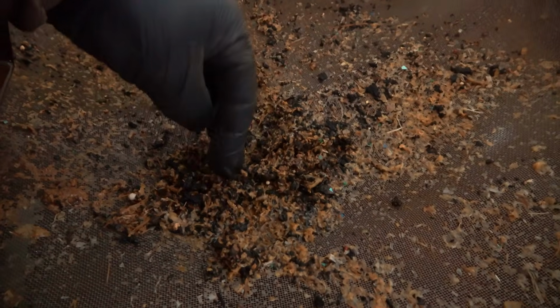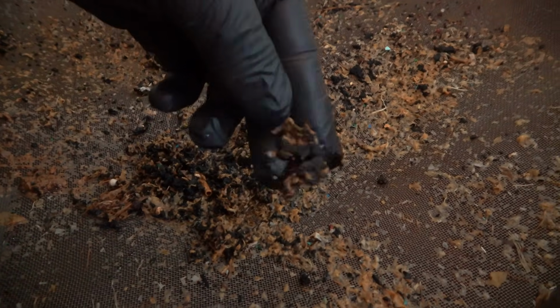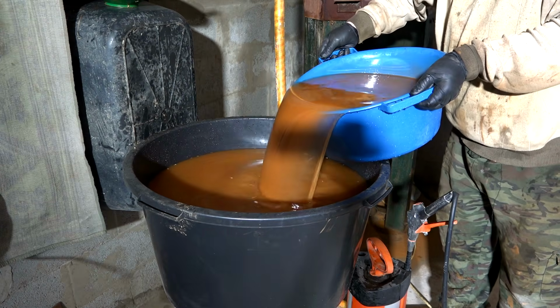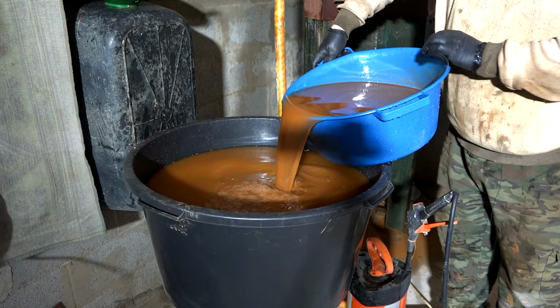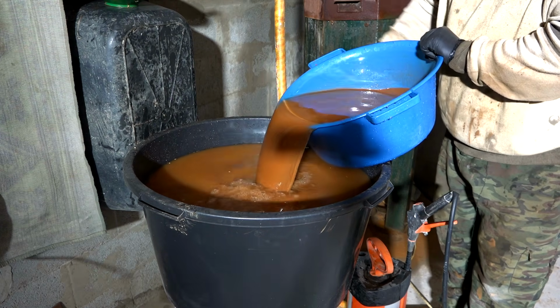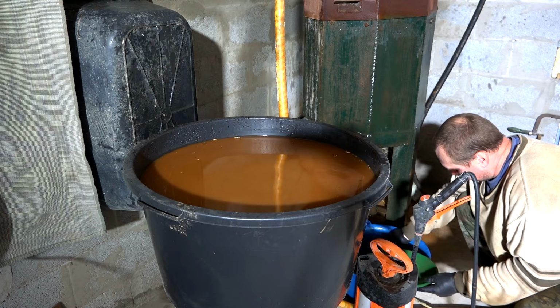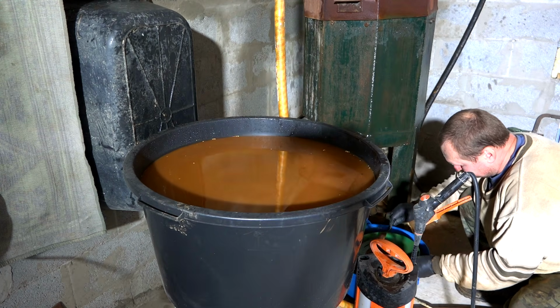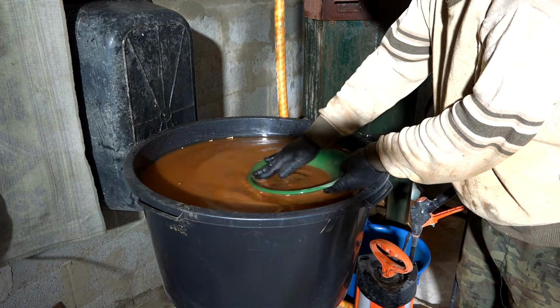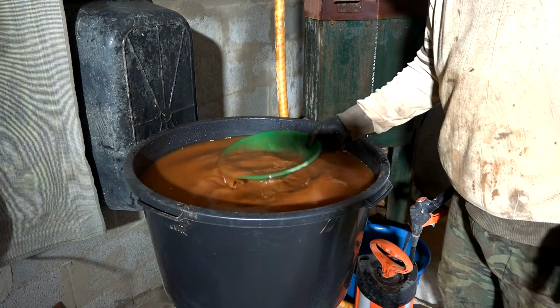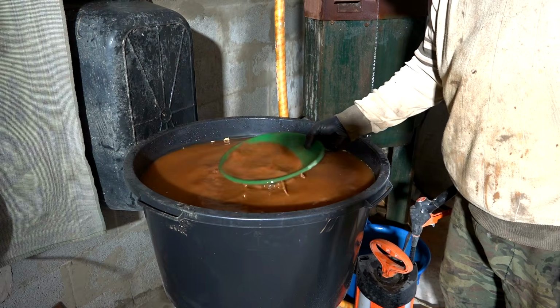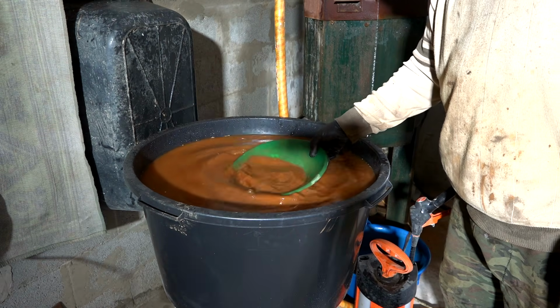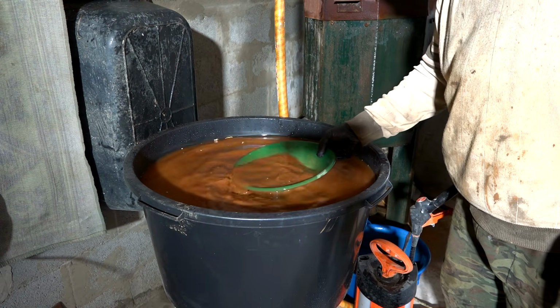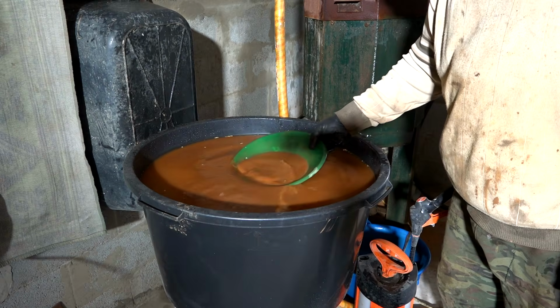A mesh is specially installed to prevent large particles from getting inside and trapping debris. Now what I need to do is collect a sample. I take a small amount of concentrate and wash it with a prospector's pan. I always do this to understand how much coarse gold was concentrated and what decisions I'll make next. Results can vary. Sometimes there's a lot of coarse gold, and we'll see how much now.